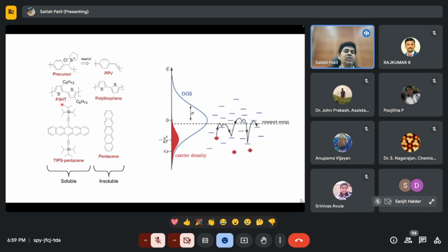Eventually, people started introducing these alkyl chains, and these alkyl chains are insulating chains. They do not participate in the transport mechanism. However, they increase the solubility. For example, if you compare polythiophene and P3HT, this is also polythiophene, but at the third position, away from the lone pair of the sulfur, you introduce such an alkyl chain to increase the solubility of this material. And as a result, you can build a very high number average molecular weight with very tight polydispersity by playing with solubility.